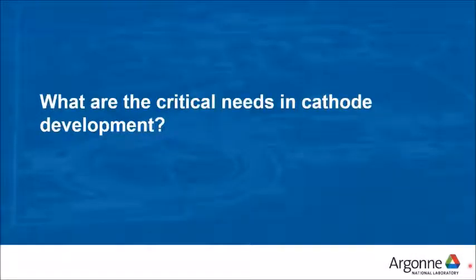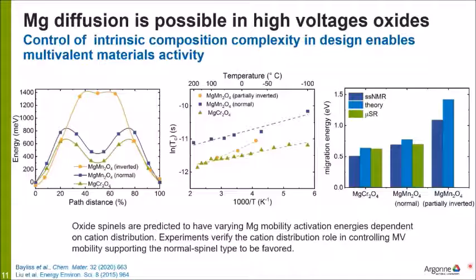So, what are the critical needs in cathode development? We know that a cathode won't work if there's no magnesium mobility at all, so diffusion. JCESR has spent a significant amount of time understanding the mobility of magnesium cations in the solid state materials for cathodes, and we did a series of theoretical nudged elastic band DFT calculations and looked at a series of different oxide spinels in relationship to changing both cation distribution, so a normal to inverted spinel, as well as compositional changes on the B site.